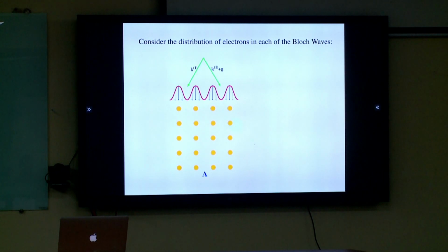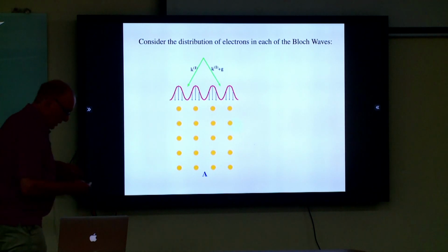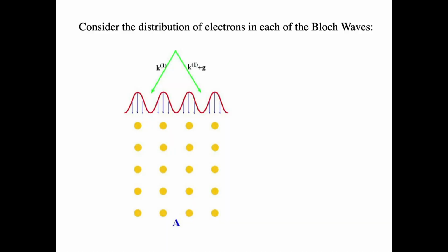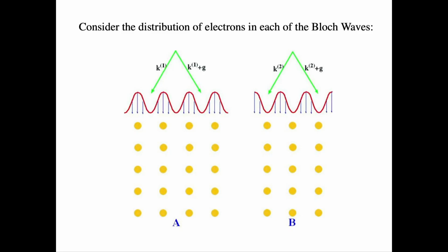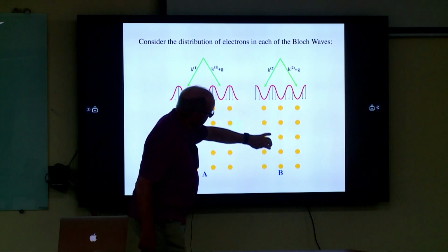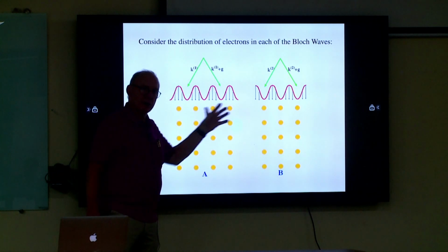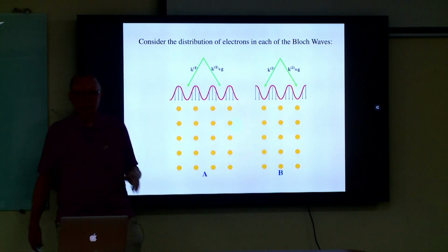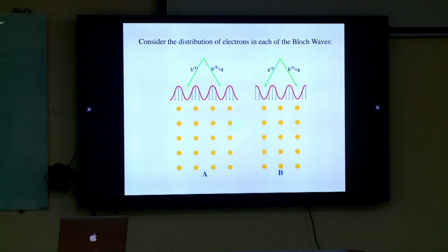And when we say scattered and when we say absorbed, it means that there's an objective aperture that's taking out the electrons. So spatially, our first Bloch wave is spending a lot of time in the scattering centers. Our second Bloch wave is spending a lot of time between the scattering centers. So we're going to say this is heavily absorbed or heavily scattered, and this is lightly scattered. And that's the first asymmetry between these two that's very important.